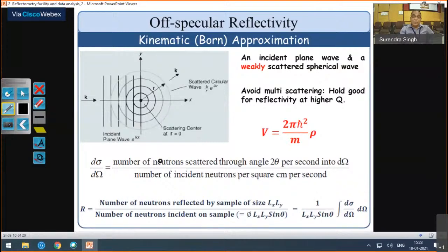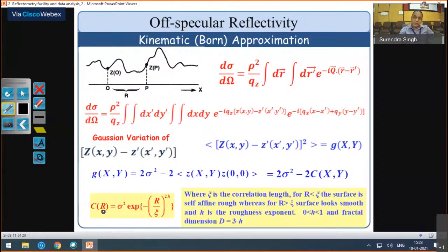So this is different. If you calculate reflectivity, you can calculate from these things: suppose phi is your neutron flux incident, which is neutron per centimeter square per second, and lx ly is the lateral dimension of your sample. Then total neutron incident on sample equals phi times lx ly sin theta, and if you calculate over all the solid angles, you get the reflectivity pattern. So we'll use the same thing.